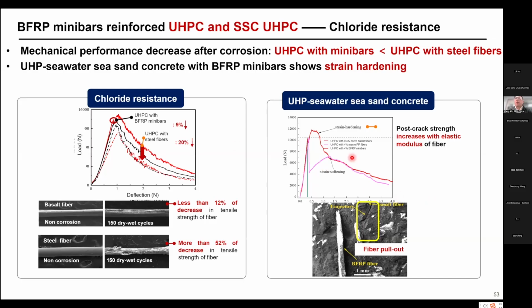And also we can use seawater and sea sand to make this kind of ultra high performance concrete using the mini bars. In this case, for SSC concrete, especially UHPSC, the non-metal one shows very good behavior. Like the basalt BFRP one, it shows better results than other fibers like PP, because its modulus is typically over 50 GPa, so it can provide a very good balance between the fiber fracture and the slippage. So we can provide strain hardening and ductile failure.